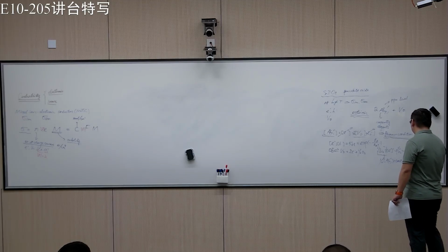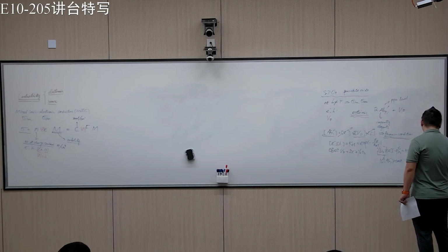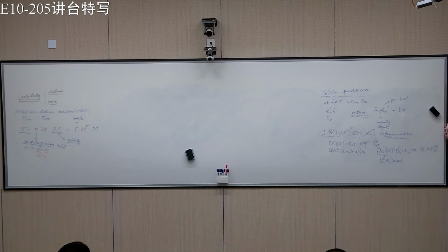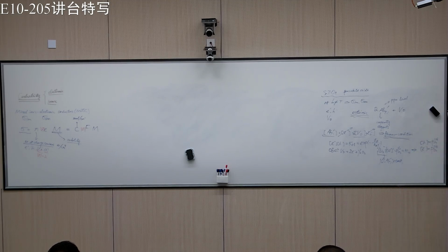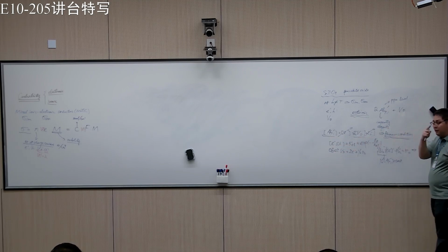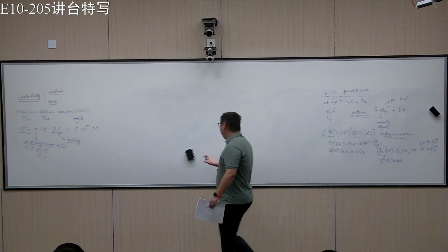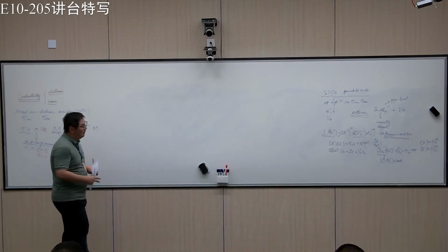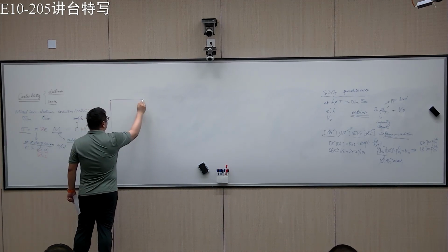Okay, so then you can see from this equation, the electron is basically proportional to pO2 to the minus 1/4, right? And the holes we know should be proportional to pO2 to the 1/4. Okay, no problem with that, right? So it's kind of like an intrinsic regime we saw before. However, in this case, it's actually extrinsic dopants which fix the concentration of the ionic defect. Okay, so we just draw the Brouwer diagram. We have just one regime for this one, so it's easier than what we solved before.